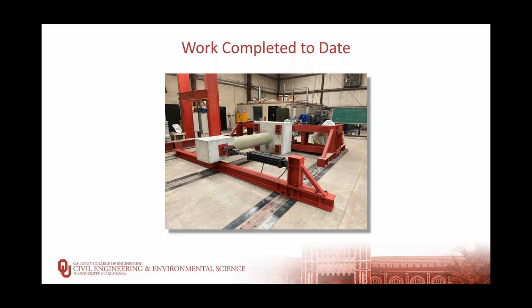We'll also record the strain gauges from the inner steel tubes and the strain gauges on the reinforcing steel for the reinforced concrete column, and we are installing strain gauges on the FRP tube near the base at the same locations as the strain gauges on the inner steel tube, except these are going to be measuring hoop stresses in the FRP tube, because that hoop stress is what provides confinement to the inner concrete core during testing.